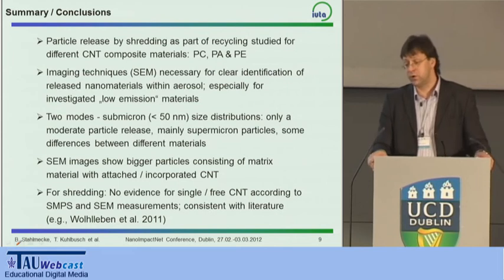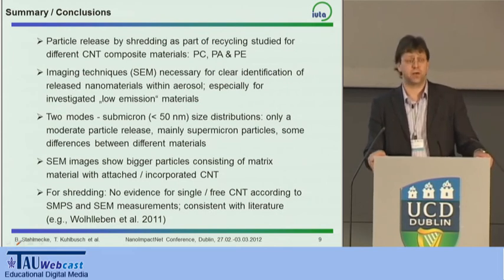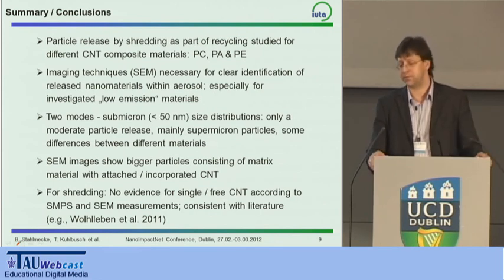So there was not really evidence that we could identify in this study of a release from the matrix itself of single fibers. And this is consistent at least with the publication that Wendel Wohlleben published last year in 2011.